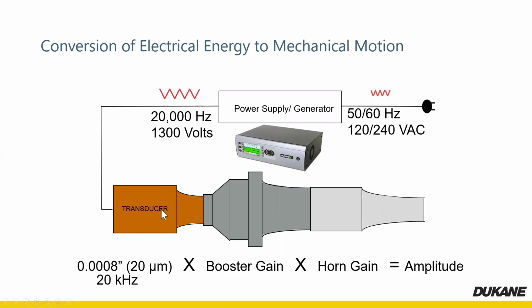We've got our ultrasonic transducer that's taking 20 microns, or 8 10,000ths of an inch, of peak-to-peak amplitude on the face of it. We then amplify that through purely mechanical means. So the booster has a mass that's above and below the nodal point. The difference in that mass gives us gain. So we've got 20 microns coming into one side. If it's a 2-to-1 ratio booster, we've got 40 microns of amplitude coming off the other side. Again, amplitude is variable, but the frequency is always fixed. So we're always talking 20 kilohertz, but what we're trying to do is get more amplitude at the face of the horn. The more amplitude, the further back and forth we're moving, the more quickly we're going to build up heat. Exactly. And Russ, your hands are perfect.